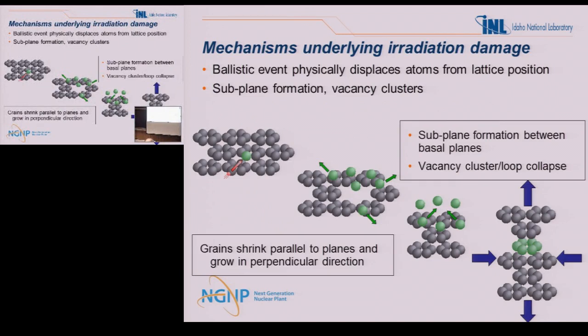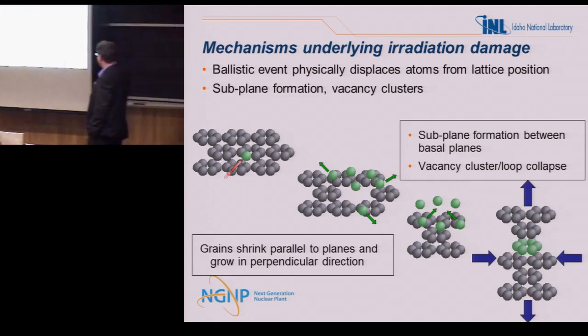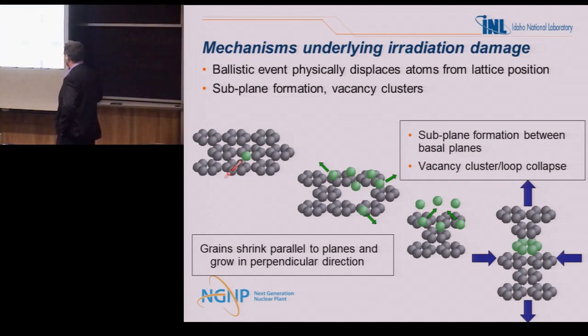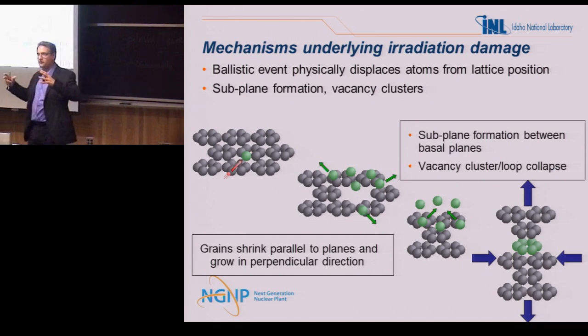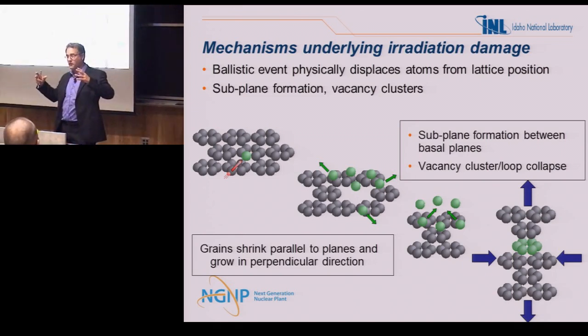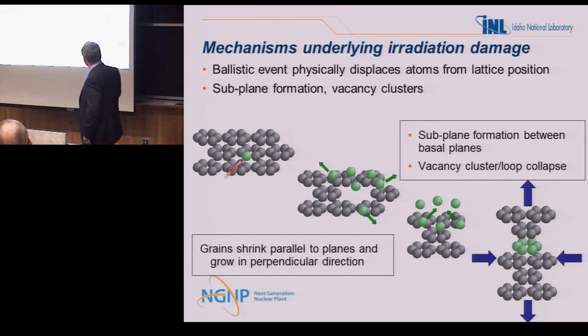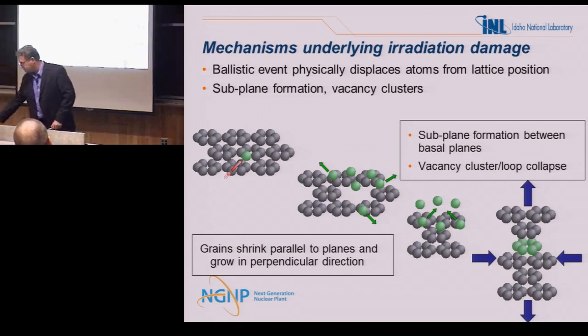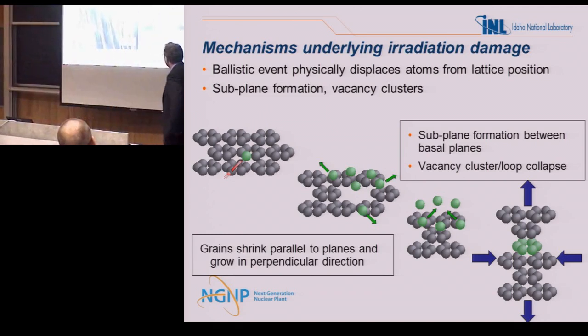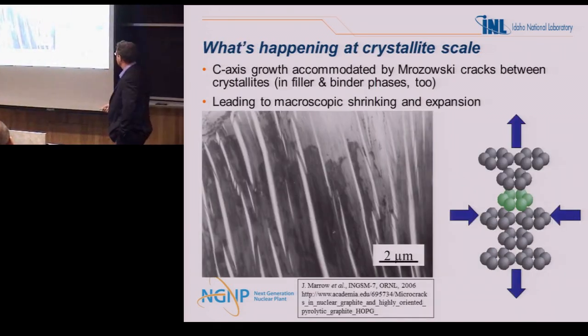So this is what's going on. You've got the neutron, it comes in, it blows the atoms out, they settle, they form into what we call subplanes, and voila, you have expansion in this direction and shrinkage in this direction because, you know, nothing like a void, nature of a void, a pore is a void, it collapses. So this is shrinking in the A direction, expansion in the C direction. This is the key to the macroscopic response.